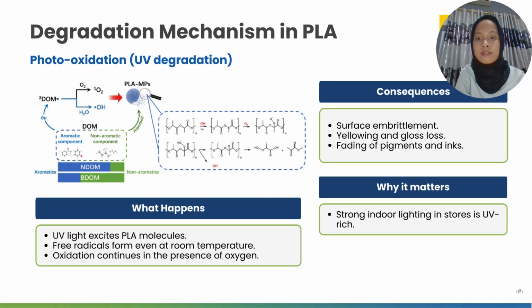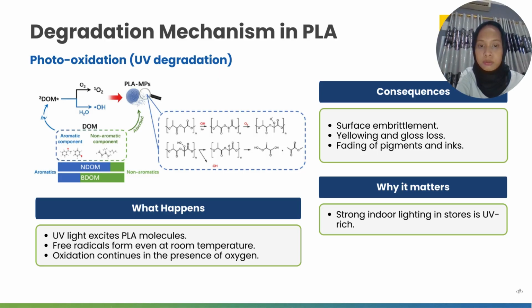Last but not least is photooxidation, or UV degradation. What happens here? UV light excites the PLA molecules, free radicals form even at room temperature, and oxidation continues in the presence of oxygen. The consequence of this UV degradation is surface embrittlement, yellowing and gloss loss, fading of pigments and inks. It matters because strong indoor lighting in stores is UV rich. So I think it's one of the causes of the UV degradation in the store.